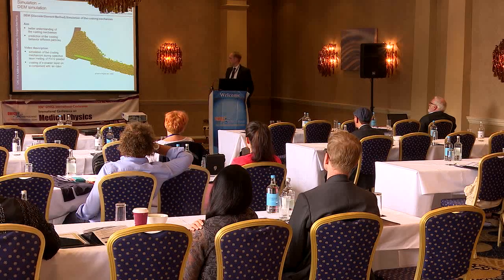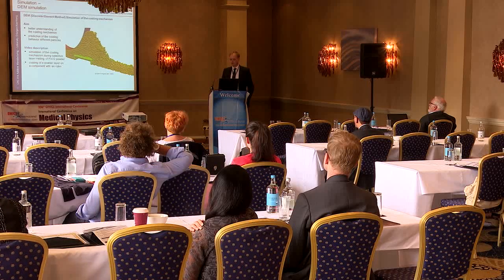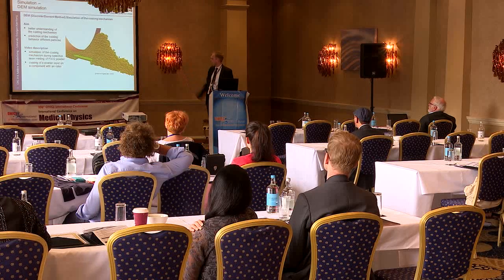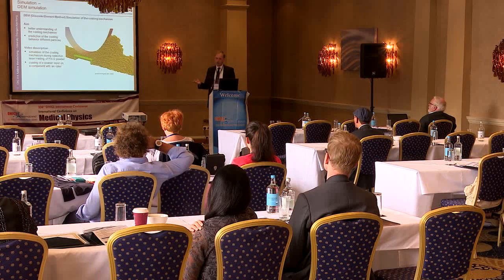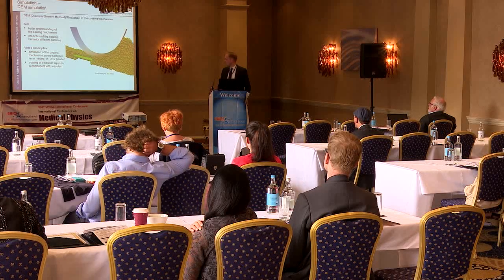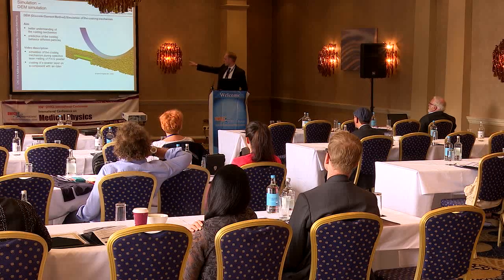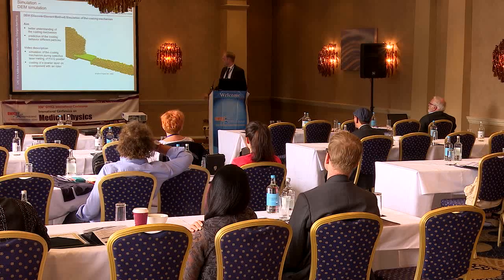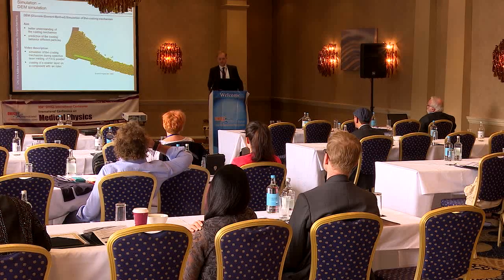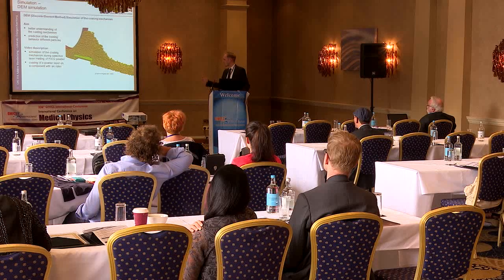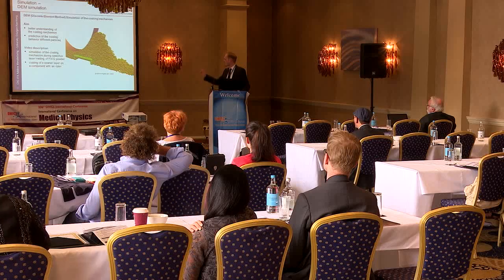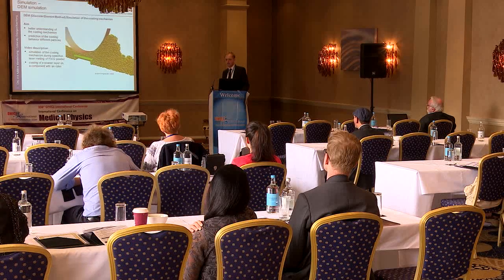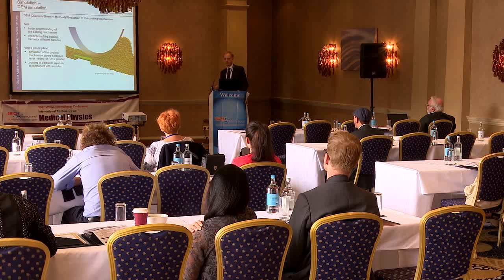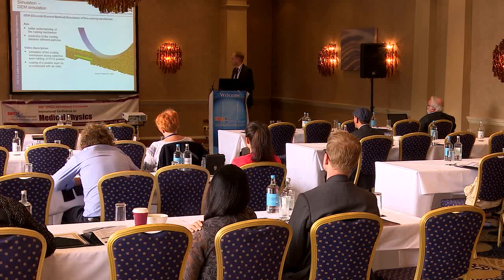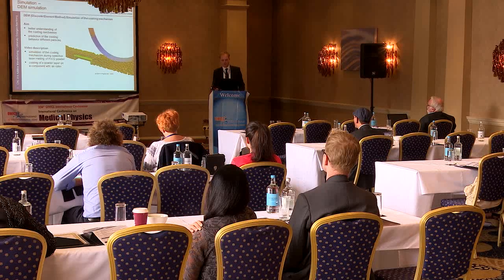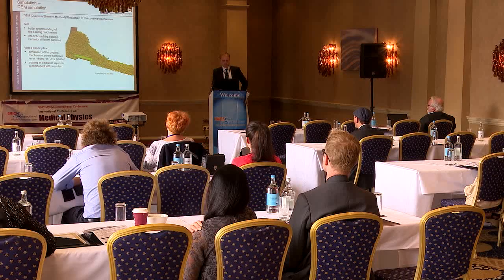This is the simulation of how the powder behaves during the coating process. What you can see in green is the part. It's already molten, or in this case solidified because it's a metal part. But then you can see how the powder is coated over this molten area. And for us, it's of major interest, because with this we can predict the packing density of the different powder particles. And clearly, when you have a high packing density, you even have better part density. So there we can test different size distributions of powders in interaction with the coating process.